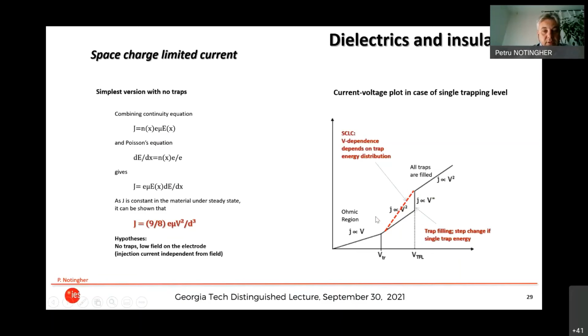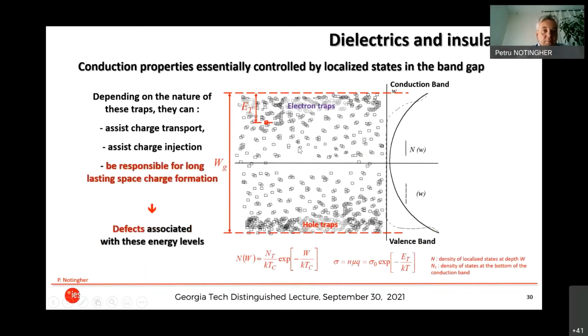So this will give you characteristics which have slopes that are superior to 1: V², V³ over d², etc. This characteristic will depend on the trap distribution and on the distribution of the energy of the traps. The most famous one is the space charge limited current, but it is not the only one. So just to summarize this, the conduction properties in an insulator are controlled by localized states in the band gap. These are caused by defects, and these traps assist charge transport, charge injection, and they may be responsible for charge accumulation, which is called the space charge formation. And in fact, they are due to chemical defects or to physical defects in the insulator.